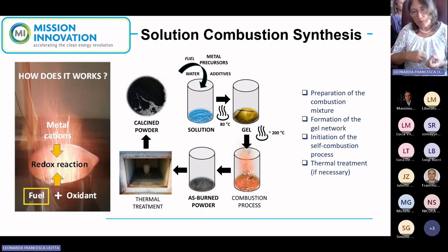And we evaporate the water until a gel network is formed. This gel network is very important because if the gel network is well constructed, we have a good combustion and a good product. The gel has the function of keeping all the components interacting with each other in position during the very fast combustion process that is activated at 200 degrees on the hot plate, and in a few seconds produces the as-burned powder, as you can see from the picture, that eventually can be thermally treated to obtain calcined powder.